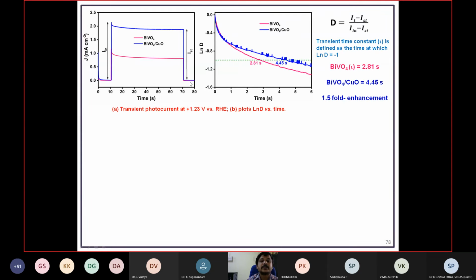Then we have measured the transient photocurrent and derived the value for the recombination lifetime from this data. The recombination time for the bare material is 2.81 seconds, but for the bismuth vanadate and copper oxide, it is increased almost 1.5 times. Normally in a bismuth vanadate electrode, the electron-hole pair recombines in a very short period. But once we make the heterojunction, the recombination process is suppressed, and the lifetime of the electron increases.